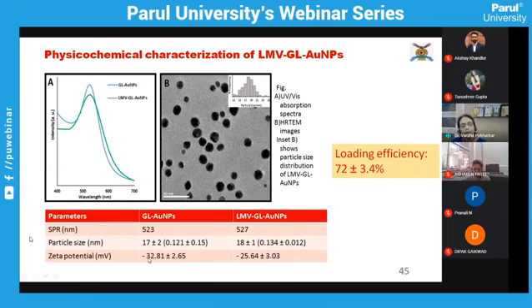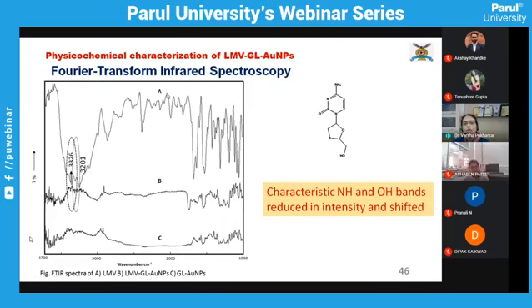The zeta potential has changed from minus 32 to minus 25 millivolts, obviously because of the cationic drug anchored onto the surface of the negatively charged particle. This change in the zeta potential itself indicated that there is sufficient loading of the drug onto the nanoparticle surface. The loading efficiency was found to be around 72%. The FTIR of the lamivudine loaded gold nanoparticle showed the characteristic NH and hydroxyl bands present in the drug, but reduced in intensity with a slight shift, which indicated that these two functionalities take part in anchoring onto the surface of the gold nanoparticle, either through hydrogen bonding or through electrostatic interactions.